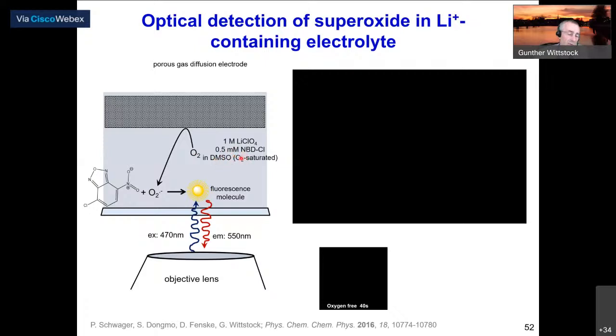So we did it in DMSO, and we suspected from bulk experiments that not only the peroxide is formed, but also the superoxide. In order to find the superoxide, we added a fluorogenic dye. That fluorogenic dye would react with the superoxide, but not with the peroxide, and form a fluorescent molecule. And that fluorescent molecule can be observed. So what I have here now, and I think I need to check back.